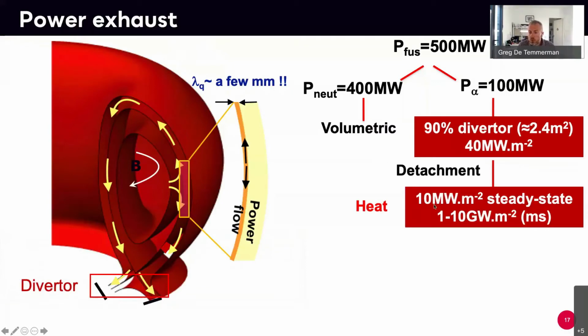and I will detail that in the next slide. Both steady states of the machine is supposed to run for a long amount of time at long durations at a time. But as we will see, there are also a lot of instabilities which are increasing the heat fluxes by 3 orders of magnitude at least in the order of a millisecond duration, and you do that at 100 Hertz, basically 100 times a second.